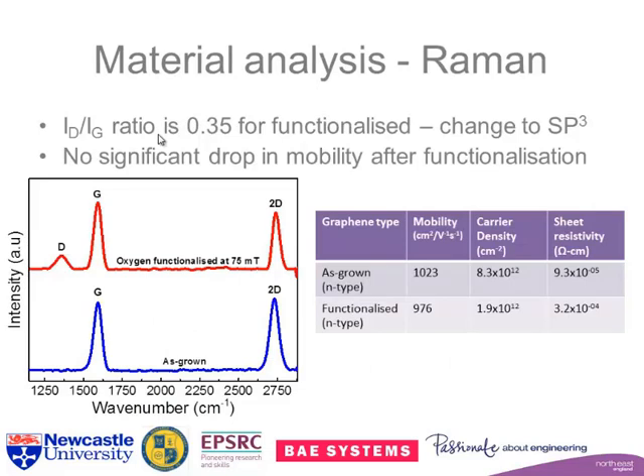We also did some Raman analysis. So as grown, we have a completely insignificant D peak, which shows that the material is very high quality. After functionalization, we do have a D peak here. This is really the sp3 characteristics of the carbon. It's an allowed Raman mode for sp3. And really it shows the disorder peak. So it changes to about 0.35, which is still pretty low.